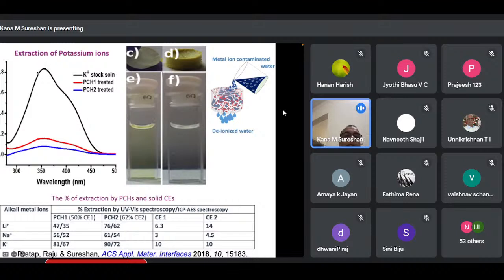This is the absorbance of picrate ion before treating. And this is after treating, of course, you can see the intensity has reduced. In 2-3 cycles, you can remove almost 97% of potassium from water. If you drink a lot of potassium containing water, that will lead to a disease called hyperkalemia, which is bad. So in such cases, one can use this kind of material to remove such potassium and other metal ions.